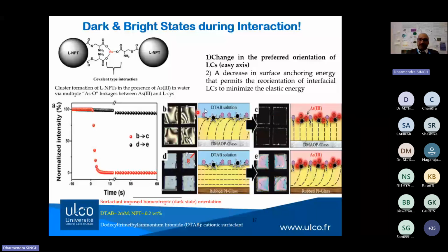So for example, here in the first row, you could see when it is present with the DTAB solution and liquid crystal interface, it is giving you the planar alignment. However, when you add the arsenic three molecules, the planar alignment changes into the homeotropic alignment.